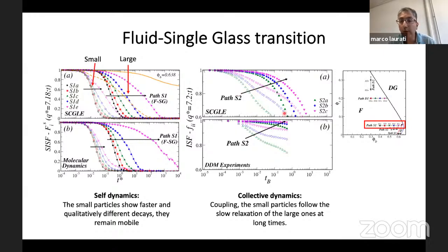And actually, we could see that the theory, of course, reproduces that also on a line where the amount of small particles was slightly different, slightly smaller, and we could get at least, even though a bit limited by the time interval accessible in the experiments, a qualitative indication of the same behavior also in the DDM experiments.